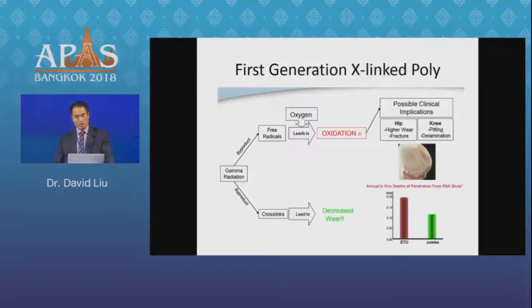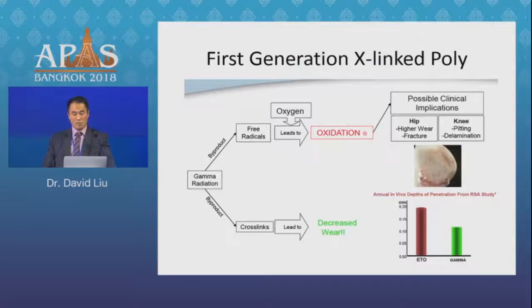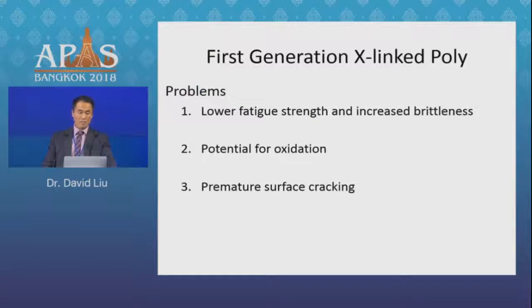So the first strategy that was undertaken many years ago was to try and improve the wear resistance of the polyethylene by cross-linking the molecules. They did this by gamma irradiating the polyethylene, which would form cross-linking between the molecules and improve their wear resistance. This did lead to decreased wear, but unfortunately it came with new problems, because one of the byproducts of this irradiation process was the generation of free radicals within the polyethylene, which then made it vulnerable to oxidation, which changed the mechanical properties of the polyethylene itself. And so we started to see increased brittleness, fatigue failure, and catastrophic failures, especially with the thin cross-linked polyethylenes at the rim of the cup.